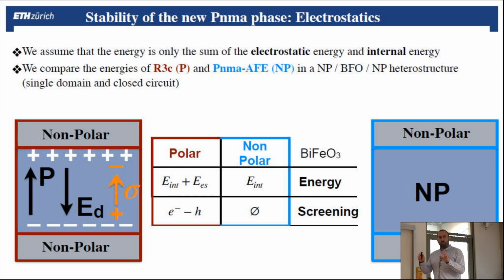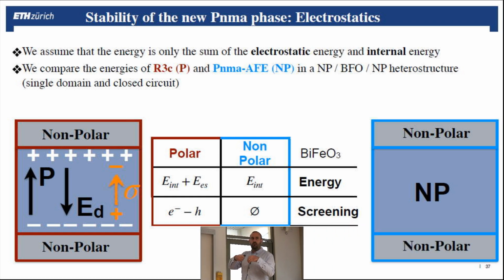And now, as this is not favorable, we assume that we don't break into domains because that was not what was experimentally observed. And we assume that there is a mechanism that the material will try to use in order to decrease this discontinuity. And this mechanism is an overestimation because there are mechanisms that would be cheaper. But to overestimate it, we assume that the material will try to screen these charges by creating electron-hole pairs above the band gap and moving them around in the material to go to the surface to screen here. So that would be the screening cost, part of this electrostatic. So the electrostatic is a positive energy, and this screening cost tries to lower the energy. In the non-polar case, there is no screening because nothing has to be screened.